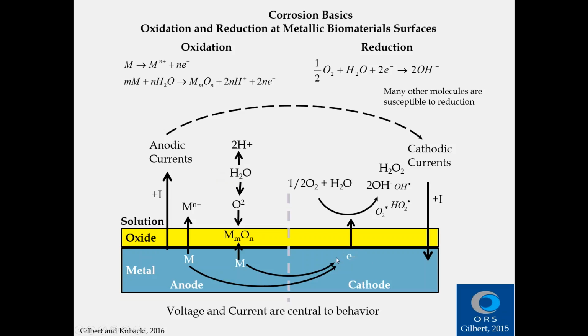These reduction reactions might be right next to where the oxidation is taking place, or in the case of, for instance, crevice corrosion in a modular taper, the reduction reactions will likely occur somewhere outside of that taper or at the mouth of the taper and are distributed over that surface. These reduction reactions take these built-up electrons in the metal surface and react them away.